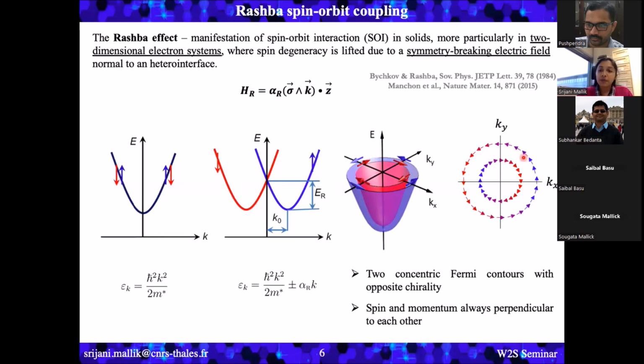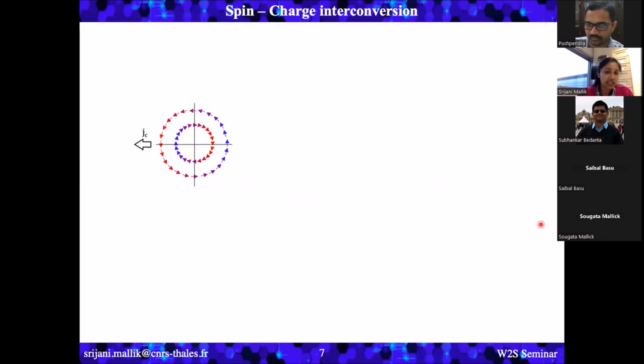So in this kind of system, if I apply a charge current, let's say in the x direction, then the Fermi contours will shift like this and there will be spin accumulations. And from here, you can clearly see that the spin accumulation for up spin and down spin are not equal in quantity, so they cannot fully compensate each other. So finally, we will end up with a finite spin density, which can also be passed through an adjacent layer.